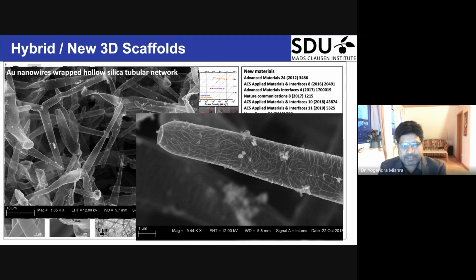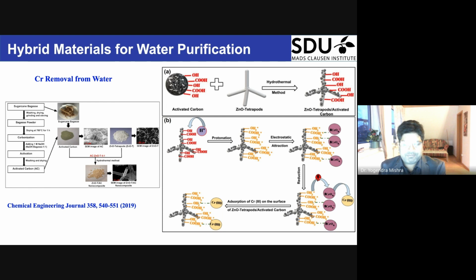Yeah, and even a very complex form of network, we could prepare: Au nanowires wrapped into a hollow silica network. So a hollow silica nanotube network was prepared using the same approach, and then gold nanowires were wrapped. So this was a very nice plasmonic composite, basically a 3D composite. So we have developed this.